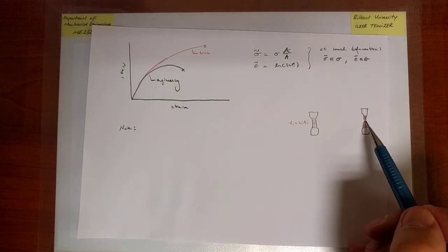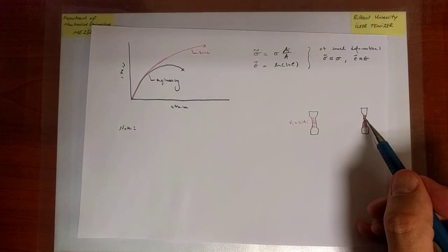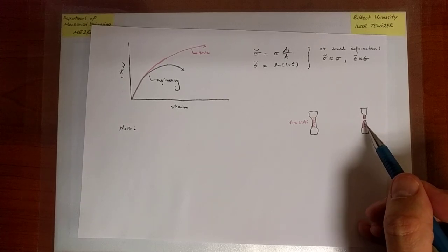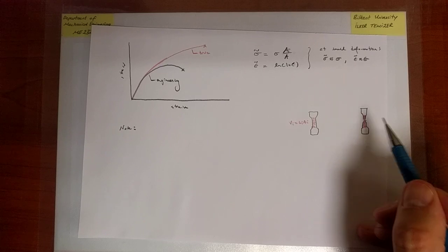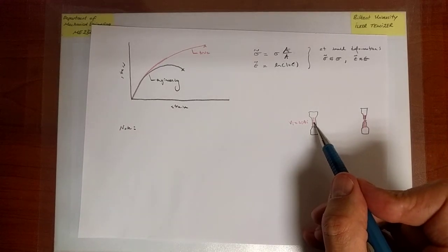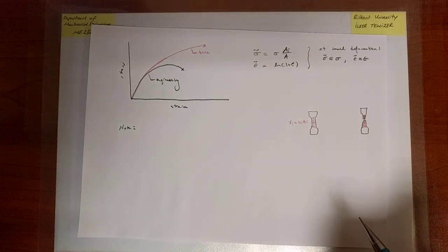So notice that when I break the specimen, all the load is removed. There is no more, let's say significant, or idealize it, let's say, there is no more elastic deformation in the specimen. There is only plastic deformation remaining. So here it says significantly and purely plastically deformed broken specimen. Here it's the undeformed specimen, and I measure the volume here, measure the volume there. It turns out that the volume is almost the same.